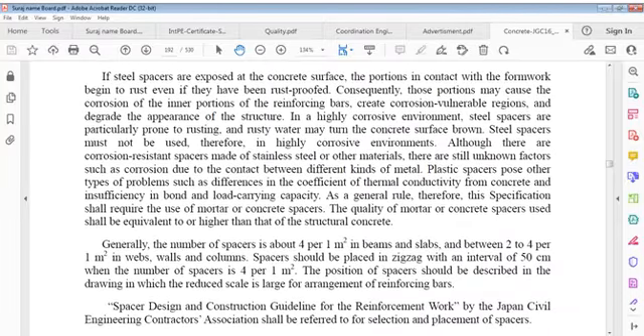at concrete surface, portions in contact with formwork begin to rust even if they have been rust proofed. Consequently, these portions may cause corrosion of inner portions of reinforcing bars, create corrosion vulnerable regions and degrade appearance of structure. In a highly corrosive environment, steel spacers are particularly prone to rusting, and rusty water may turn concrete surface brown.